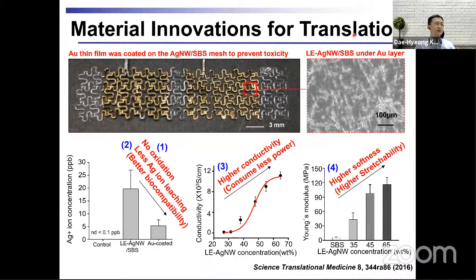Although we proved the efficacy of the concept, we still had many issues toward clinical translation. In particular, we had many issues in material. For example, silver nanowires can be easily oxidized. And if silver nanowire is oxidized, then the contact resistance between silver nanowires will increase a lot. So inside the animal body, as time goes, the conductivity will continuously decrease because of the oxidation of the silver nanowires. Also, inside the biofluids, silver nanowires can be dissolved, and silver ions can be leached out, and such silver ions are toxic. So we have to solve the biocompatibility issue.